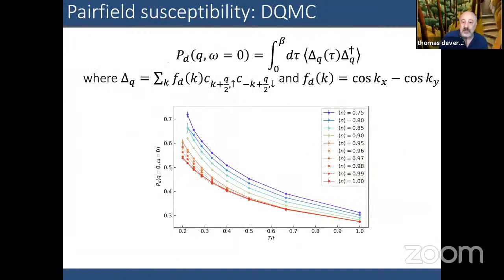But let me show you the determinant quantum Monte Carlo, so not DCA, and just show how far we can get by showing you the temperature evolution of the D wave projected pair field susceptibility. So here you can see for a wide range of doping, the pair field susceptibility grows as one decreases temperature for all doping. And in fact, the pair field susceptibility just increases off of half filling, and there's no non-monotonic behavior. It just seems to continue to go up, with the largest being at 25% doping. So that's for the pair field.